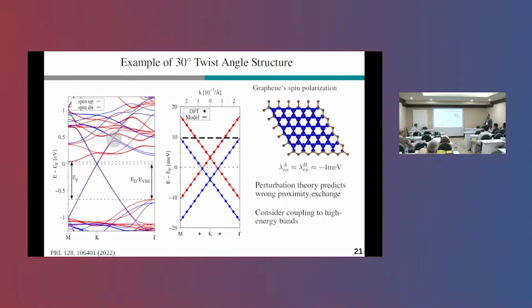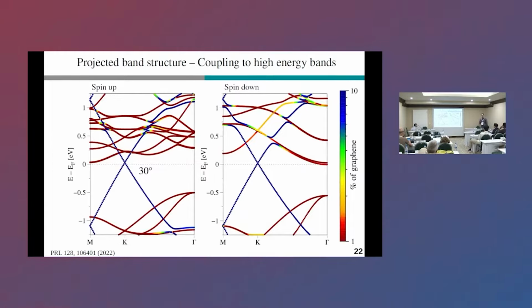And another way to look into this is within the framework of the projected band structure. So this is again the full dispersion, but now decomposed into spin up and spin down manifolds. And the color code tells you something about the percentage of graphene within these states. So blue color means it's pure graphene, red color means it is substrate, and these rainbow colors indicate the coupling.